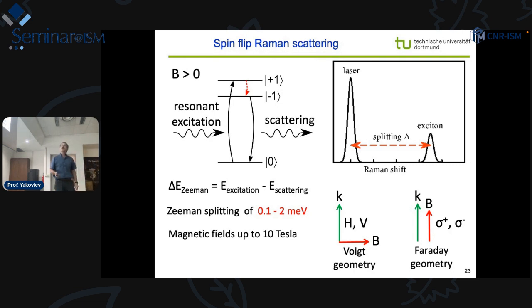But you can use this technique also to study small Zeeman splittings, for example, for the excitons and for the carriers. In this case, we resonantly excite the exciton resonance, and we apply a magnetic field. So we have a Zeeman splitting in magnetic fields, and these Zeeman splittings are rather small. In our magnetic fields up to 10 Tesla, they're in the range of 0.1 to 2 millielectron volts. So we need a huge spectrometer and to play several tricks to subtract the reflected light or the laser line, which is strong itself, but it's doable.